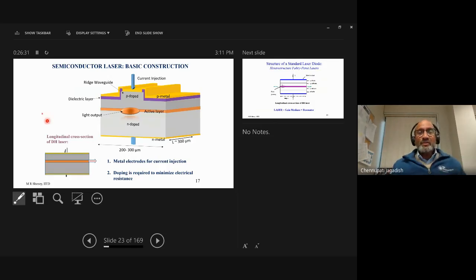Here you can see more details of this particular semiconductor laser. Instead of just having N-type and P-type semiconductor, you have something called an active layer. You also try to create a waveguide here, put a silicon dioxide dielectric layer, put some metal, and then selectively inject carriers from the top, and of course make a contact at the bottom as well. Thereby you're able to inject carriers and guide the light along this waveguide, which allows the laser to work. Again, the doping is important to reduce the electrical resistance of the device and to make good low resistance ohmic contacts.